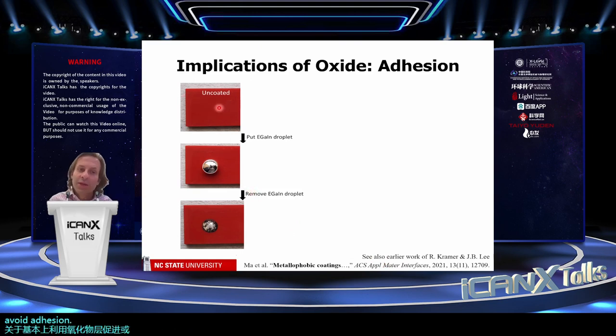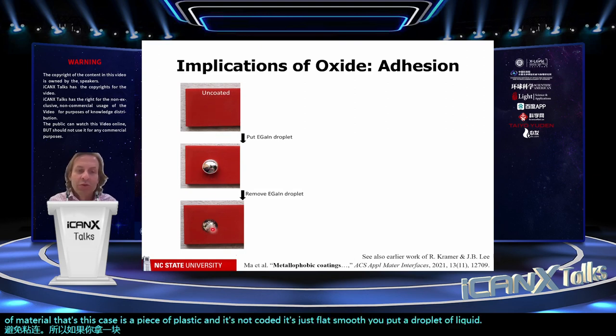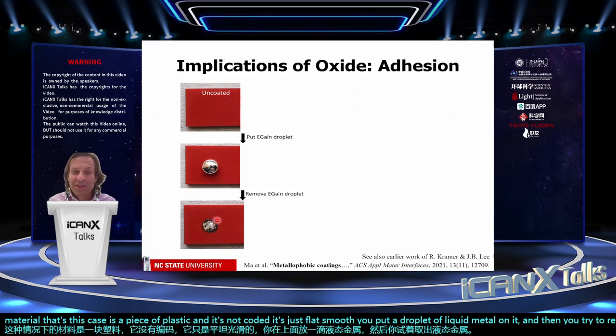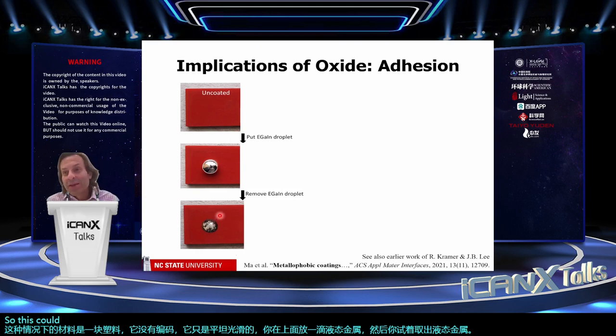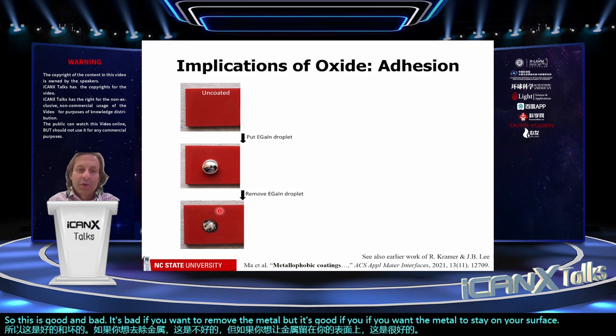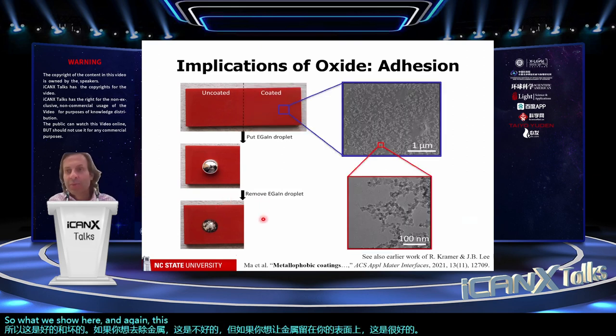So if you take a piece of material, in this case a piece of plastic, and it's not coated, it's just flat, smooth. You put a droplet of liquid metal on it, and then you try to remove the liquid metal. It sticks to the surface. So this is good and bad. It's bad if you want to remove the metal, but it's good if you want the metal to stay on your surface. So what we show here, and again, this is building off prior work, is that if you coat the surface with particles or something to make it rough,